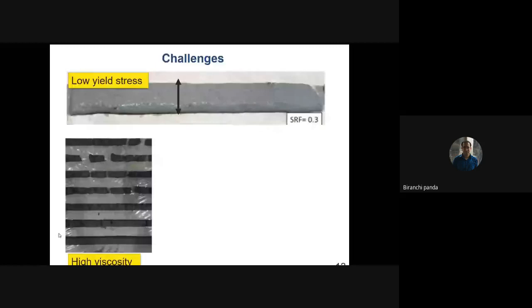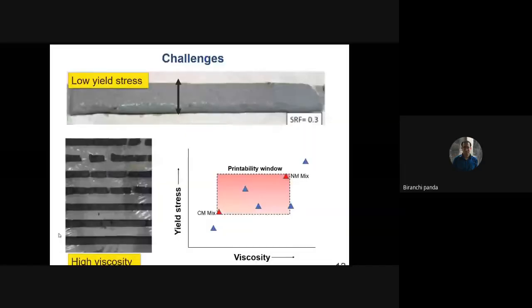So we need to have an optimum material combination so as to print the material. We have to properly create a balance between yield stress and viscosity, and thereby come up with a printability window where these mixed combinations will be printable. Okay. So when I say printable, it means the material should be extrudable, maintaining its own shape, and buildable. We also need to deposit more layers. Okay. So how can it be done?